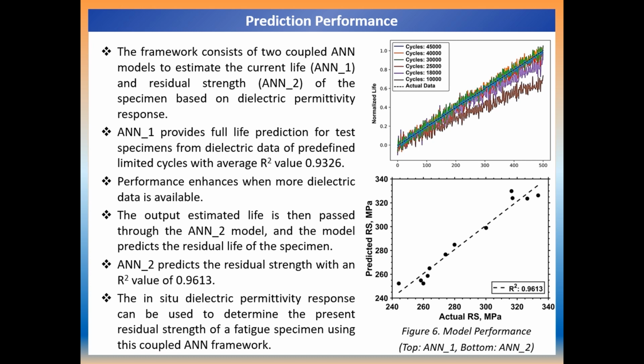To determine the framework performance, the measured real permittivity data at limited cycle fatigue was passed through the ANN1 model to estimate a specimen's life at that instant. The output predicted life is then passed through the ANN2 model, and the model predicts the residual strength of the specimen. As you can see, ANN1 can predict actual lifespan of a test even from early life dielectric response. As dielectric data up to more life level is tested, the model's performance increases. The overall framework can predict the residual strength of a specimen from dielectric permittivity with an R-square value of 0.9613.